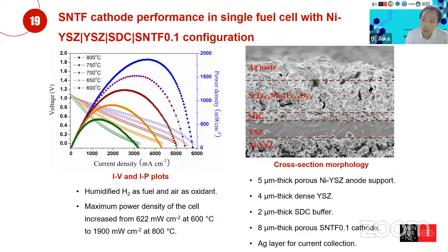If you ask me why we are using this kind of structure, it is because we want to ensure that there is no leaking of the ionic species. Sometimes SDC in here, although we categorize it as an ionic conductor, if it is exposed to the reducing atmosphere, which is the hydrogen, then it may have a little bit of electronic conductivity. Okay, so with this kind of structure, we ensure that there is no leaking of the ion from the cathode to the anode side.